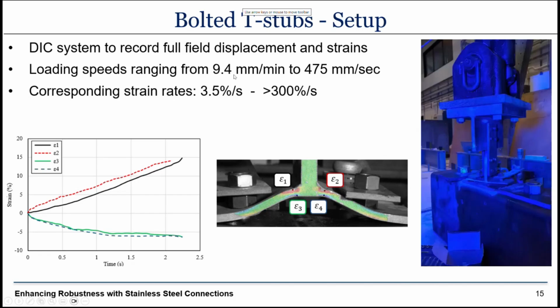So we went from 9.4 millimeters per minute for the quasi-static loading conditions to 475 millimeters per second to induce higher strain rates. And the corresponding strain rates that we measured using digital image correlation reached up to over 300% per second for the 475 millimeters per second loading speed.